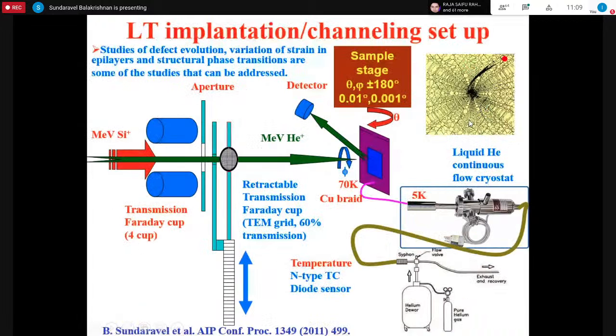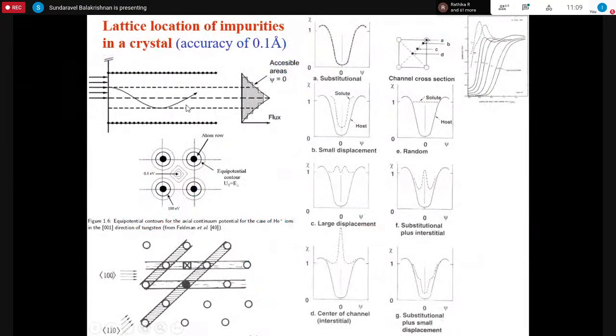And if we connect a cryostat to the sample holder using a copper braid, the sample temperature can be lowered, and we'll be able to do channeling at lower temperatures also. When we align this beam with respect to the crystallographic direction, at the center of these atomic channels, we'll have higher incident ion flux, while towards the outer edge of these channels, there will be lesser flux. And if you take this tilt angular scan about these directions, we look at the signal from the substrate as well as the dopant atoms. In case the dopant atom is substitutional, then such dopant atoms we are marking with these dotted lines.